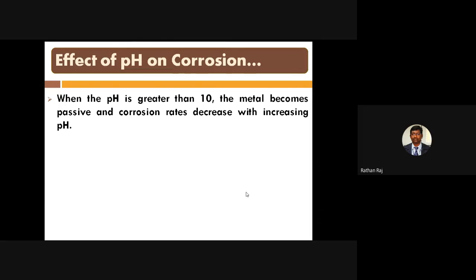So what is actually the effect of pH on corrosion? The reinforcing steel in the concrete is usually in the passive state, as we know, because of the high alkalinity of the concrete, due to the concrete pore solution. However, the passivity may be lost and corrosion occurs on the steel by the decrease of pH due to carbonation. As already told, the carbonation does not happen immediately.